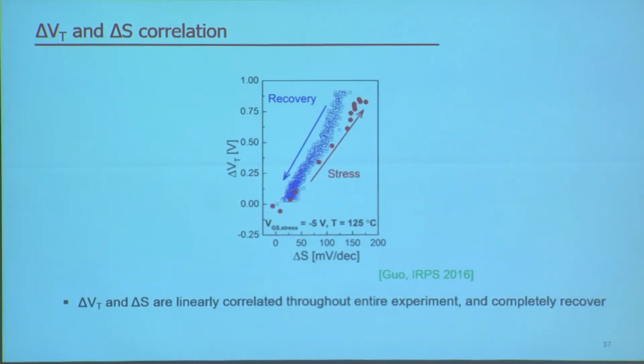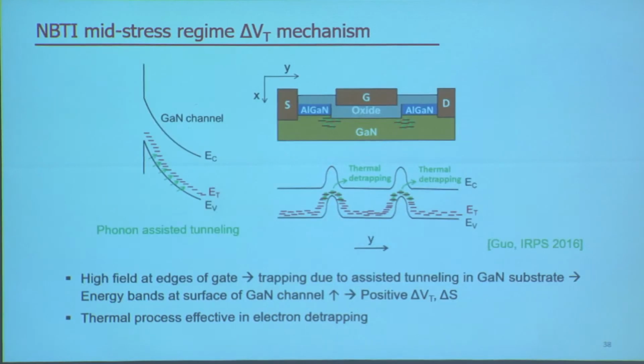Here is the correlation of delta VT versus delta S throughout stress and recovery. And you see that they're very well correlated. Again, it suggests that the change of delta VT and the change of delta S are probably from the same single mechanism. So what we believe is happening is a phonon-assisted tunneling process where the electrons in the valence band can tunnel through the deep levels within the gallium nitride channel. And this could happen at the edges of the gate, underneath the gate, when we supply a negative gate bias stress.